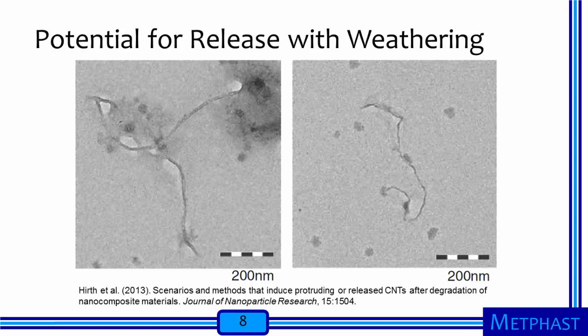nanotubes could be released. The image on the left shows a free nanotube released after the test material weathered with ultraviolet radiation was agitated for 30 seconds using an ultrasonic probe. The image on the right shows a free nanotube released from the test material weathered with artificial rain cycles after ultrasonic agitation. While these are laboratory observations under highly controlled conditions, the experiments show the potential for releases of carbon nanotubes into the natural environment after engineered nanomaterial products experience weathering followed by mechanical stresses.